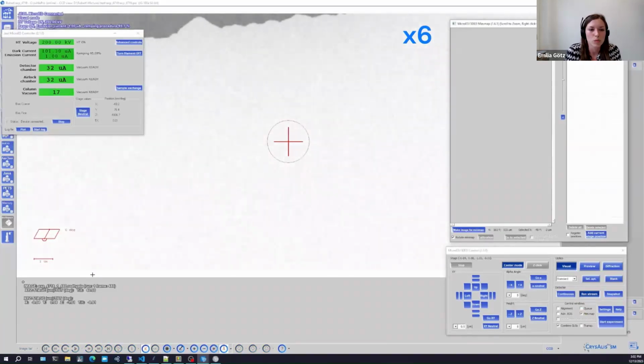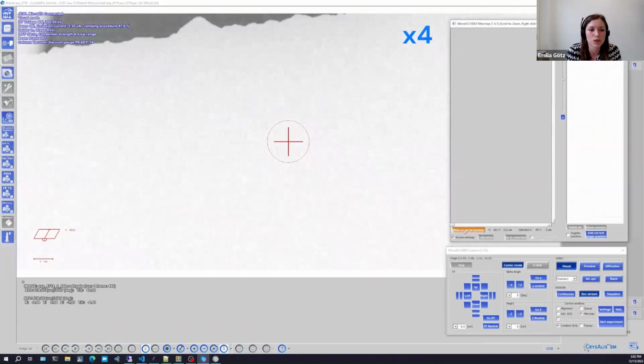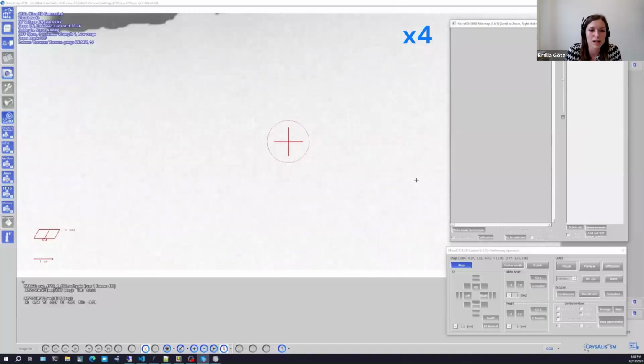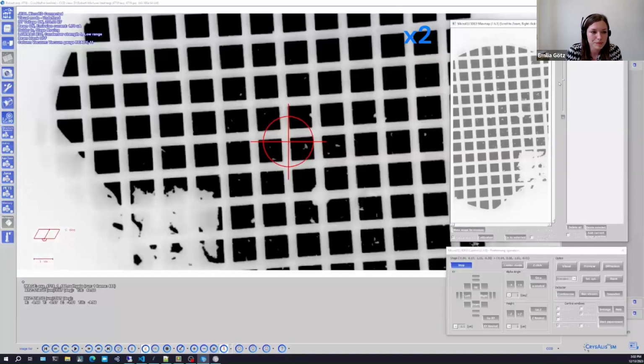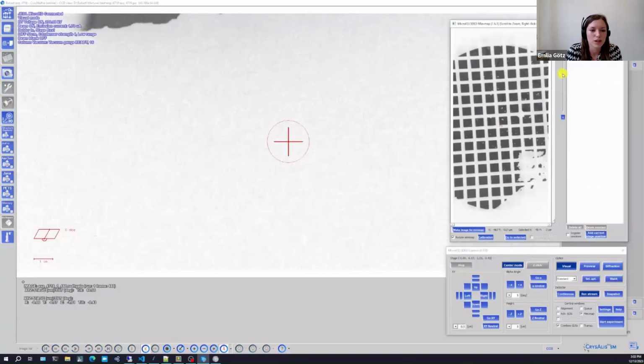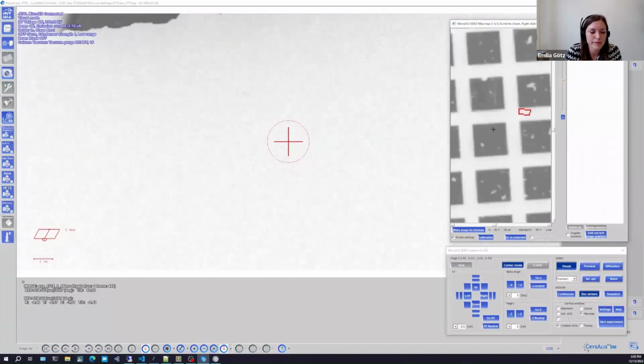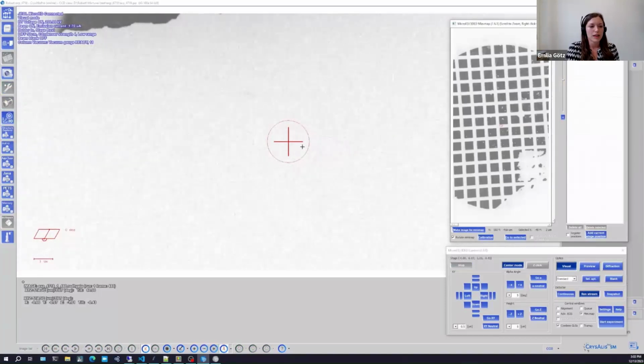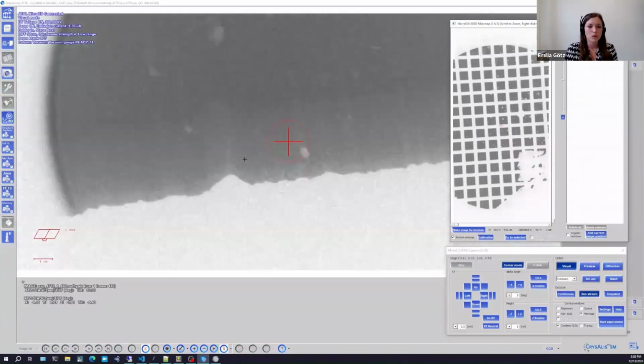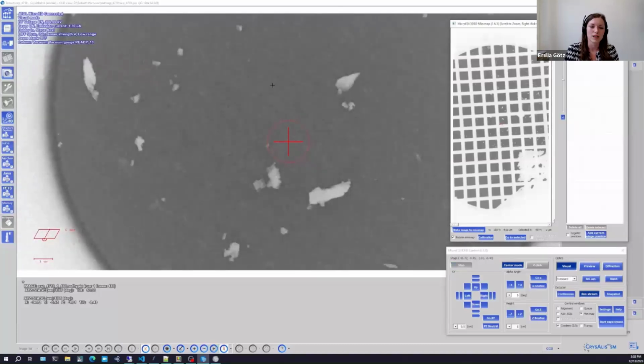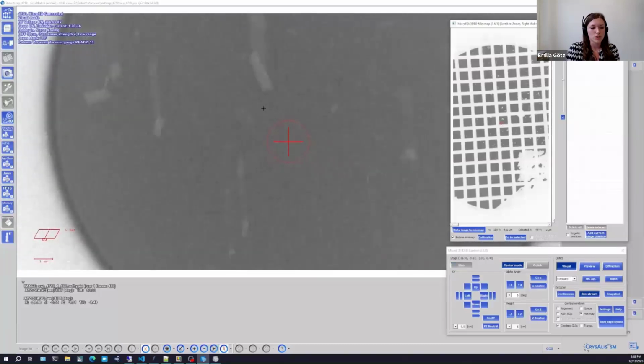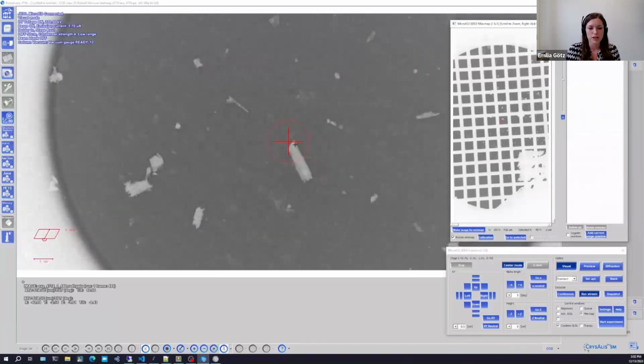And then once our beam is fully on, the first thing we do with a new sample grid is to take a very low magnification image of the entire grid, which is called minimap. And in the minimap window, we can then change the level of contrast with a slider, as well as zoom in and zoom out. Back on the grid, we can then navigate either with a trackball, which is the most familiar thing to the electron microscopists, but we can also directly point and click on the screen, or we can go to a selected position on the minimap.